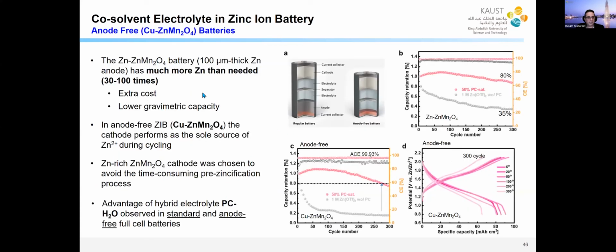And then we are also trying to work with these anode-free batteries. Anode-free batteries, why? Because there's a 100 micron thick zinc, and we only use a fraction of it. This is really a total waste. It also reduces the gravimetric energy density. So we use this cathode, and we use it with a copper anode without any anode zinc. And we can make these batteries. These batteries still need a lot of work, I have to be honest. But look at the difference between the pink and the gray here. For anode-free, this PC also gives you an advantage. You can see it here, also with a 99.93 Coulombic efficiency. And you can also see the charge-discharge.